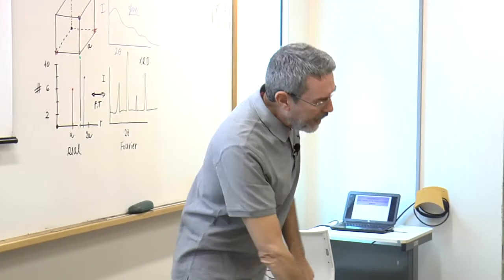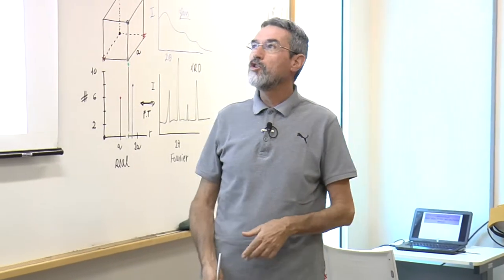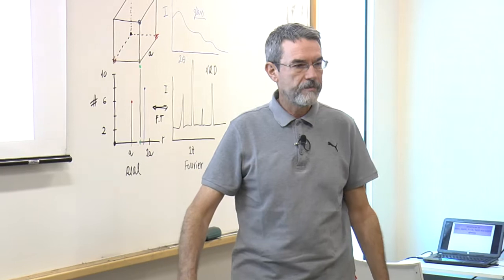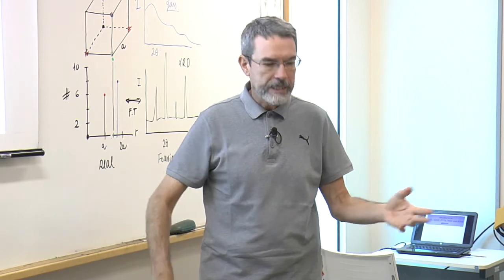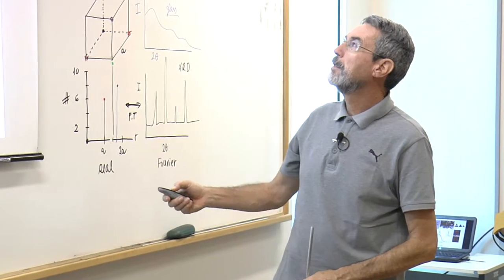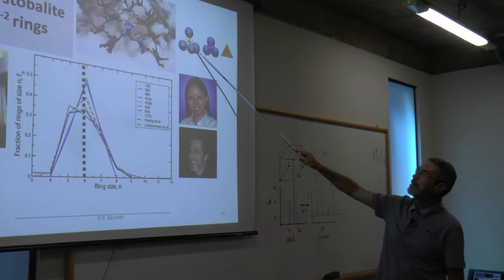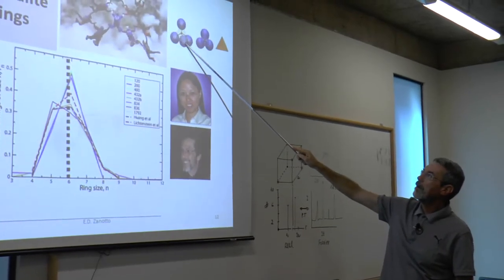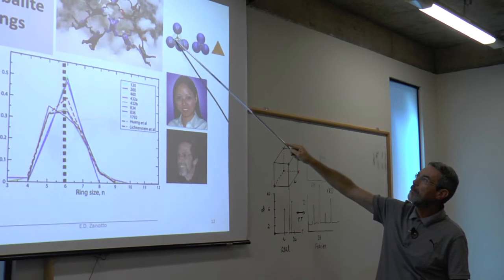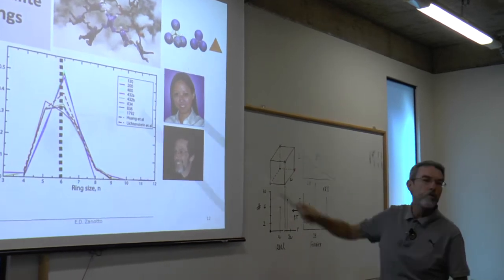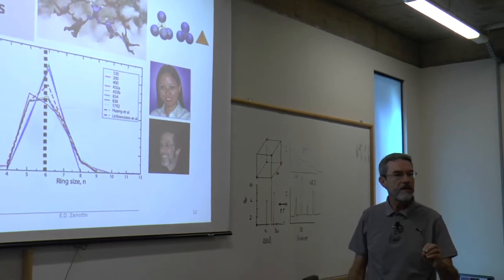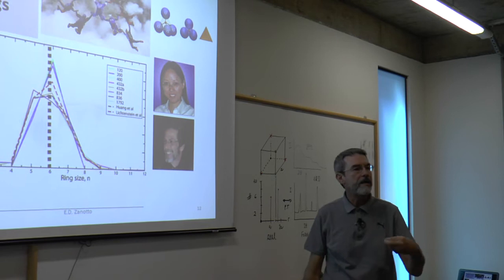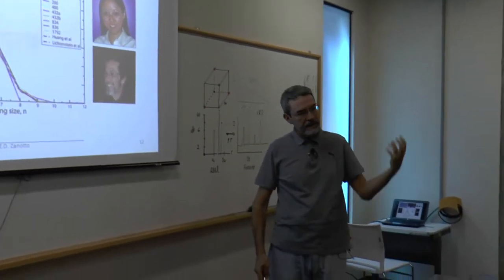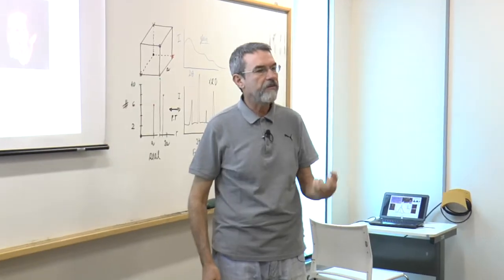So let's take the 5 most common oxide glass formers. Silica glass is tetrahedral, as I have shown here. This is the structure of silica glass. Silicon, oxygen, oxygen, oxygen, oxygen. The distance here is about 1.5 angstrom. This distance here is about 2.5 angstrom. This is the unit that assembles the structure of silica glass, the fundamental unit.